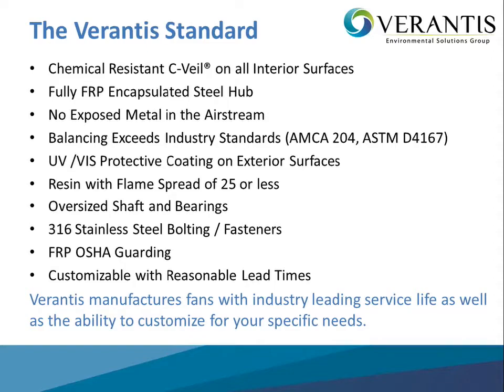Our balancing exceeds industry standards. As I mentioned, we have a UV protective coating on the exterior surfaces. The resins that we choose to use have a flame spread rate of 25 or less. We have standardized on oversized bearings and shaft in order to increase life expectancy. We also use 316 stainless steel bolting and fasteners, FRP OSHA guarding, and our product is very customizable with reasonable lead times.